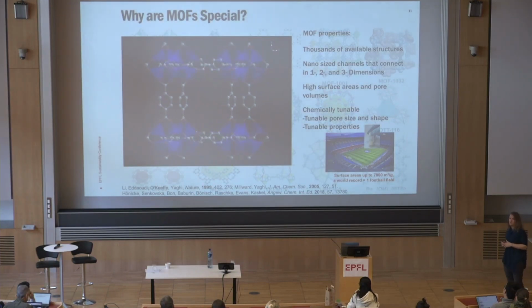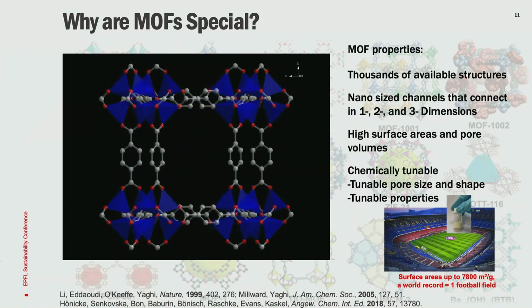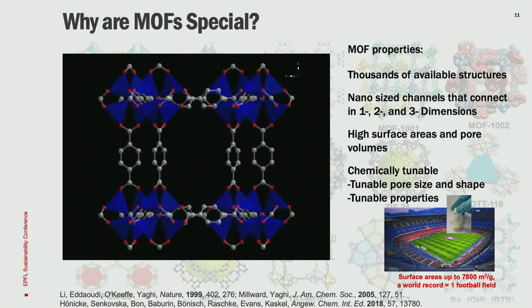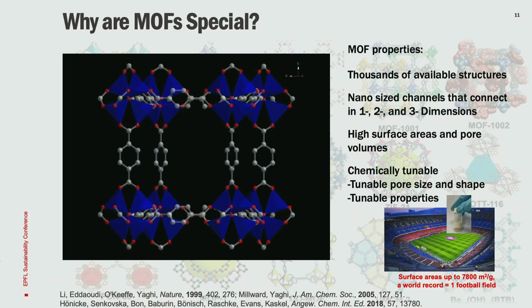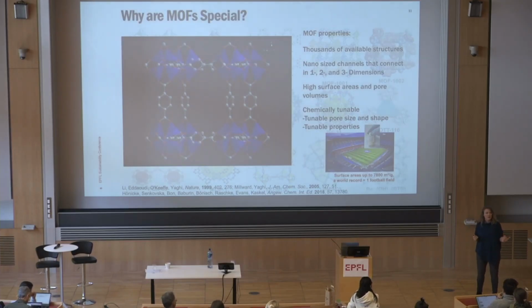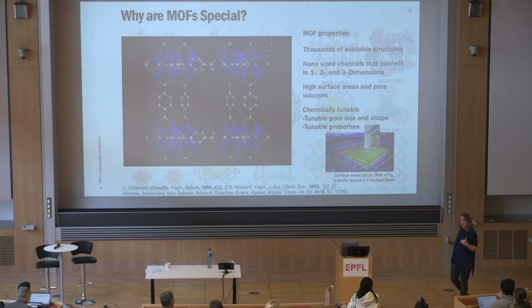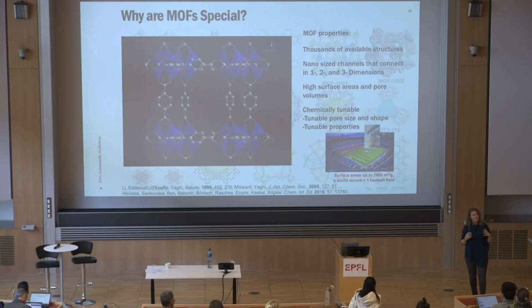So here is the prototypical metal organic framework I'll refer to as MOFs from this point forward. You can see the metal clusters here in blue. These are interlinked by these organic units shown in gray. What I note is that the materials, the walls, are really atoms thick. They're mostly open space, okay? And this is really what gives rise to these record surface areas. Just like you can access the external surface area of the material, like you can on the table, you can also access every part of the inside as well, if that makes sense. And so that's what gives rise to these record high surface areas.